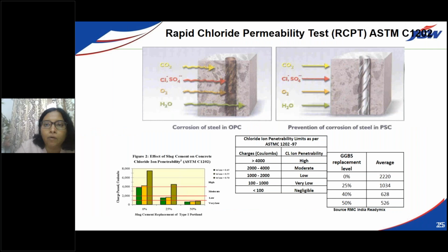We move on to rapid chloride permeability test. This is a very easy test, and it is very easy to do it in the laboratories. If we see the various replacement of GGBS, 0%, 25%, 40%, 50%, we see normally with 50% replacement of GGBS, the rapid chloride penetration, the charges which are passed are very, very less. This is approximately 500 to 600. If there is only OPC in the system, you can see it goes beyond 2000. Sometimes it goes up to 3000 to 4000.